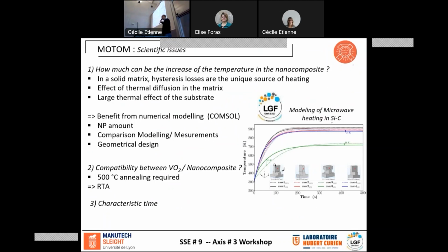Another scientific issue in terms of elaboration is the compatibility between both materials. It is supposed to work, but we are not so sure. We have not done that before because of the annealing which is required, and perhaps we will use rapid thermal annealing. And another question and issue is about the characteristic time of the effect. How much is the transient behavior in our case, how much time to obtain the static behavior, and so on.